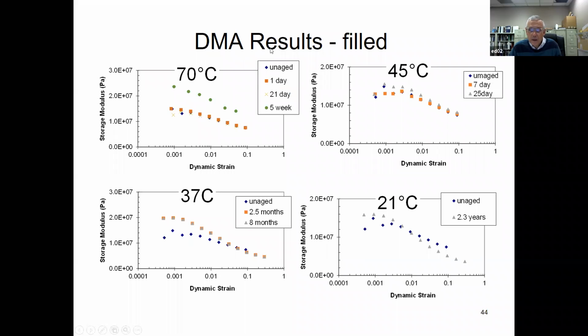Okay, so here are our DMA results of the filled compound. So here's the unaged, 1 day, 21 day, 5 week. And then so on for 45 degrees, 37 degrees, and 21 degrees. So we looked at the low strain modulus. I think we used the modulus at 0.1% as our metric.